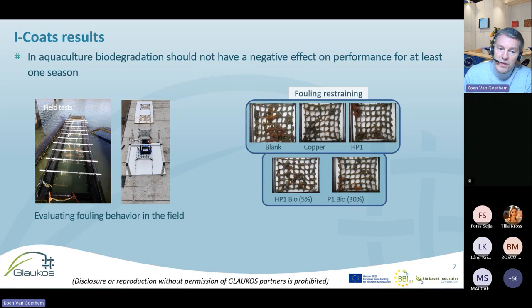So we took the bio-based coatings, we applied them on small nets, as you can see here, and we hung them out in the field to see, okay, after how many, I would say, months. At first we talk of days, of course, then you talk of months, and how long actually can these coatings stay on the nets and protect the nets with, of course, an additive component like you see here. This is without anything, with copper, or as you can see, the HP1 was with a bio-based net. At first we tried 5 and then we went for 30%, 35 if you want. That's the same area, and yes, we do see a fouling restraining effect, which is positive and which of course is important for this industry of aquaculture.